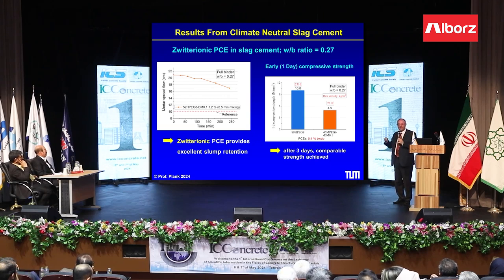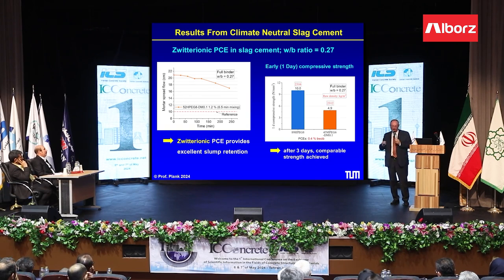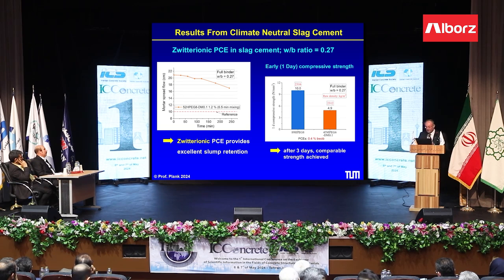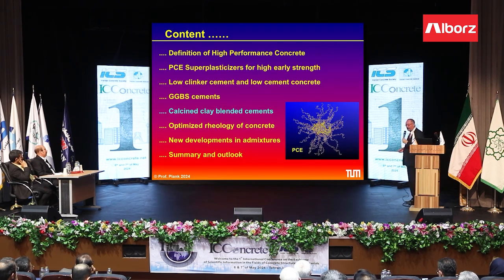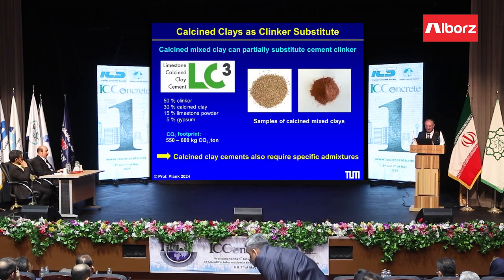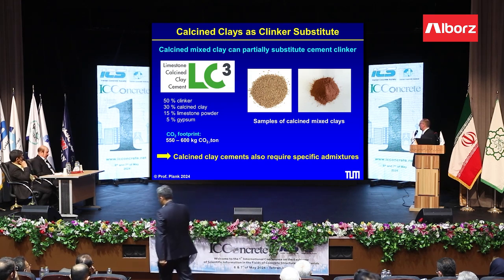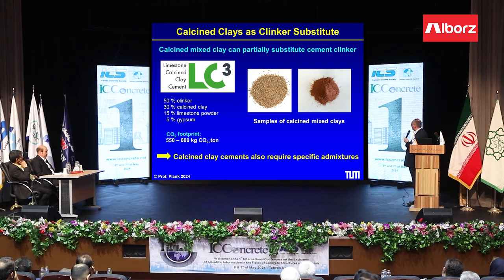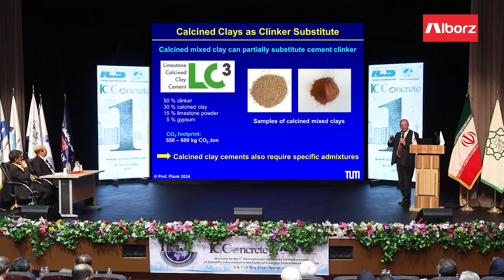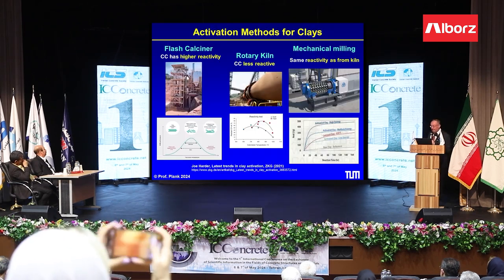So what I want to say is these new green binders require differently composed admixtures. We have to change the molecules to be effective in those systems, and the PCE industry has many ideas how to accomplish this. Now, calcined clays are talked about a lot, especially LC3. And here you see the LC3 formulation, 50% clinker, 30% calcined clay, 15% limestone powder and gypsum. This has a lower CO2 footprint, but it is not climate neutral. So it's a big step forward, but it is not what we really need to accomplish. And therefore, we are working very hard to improve it.